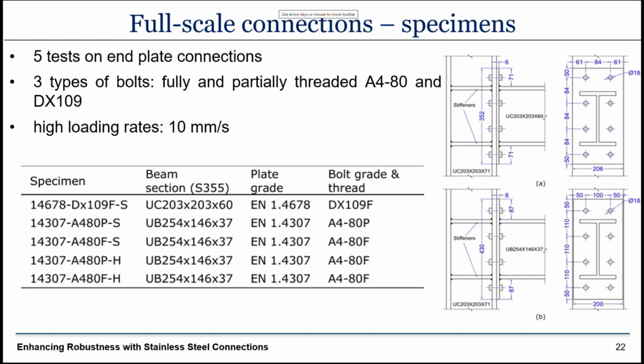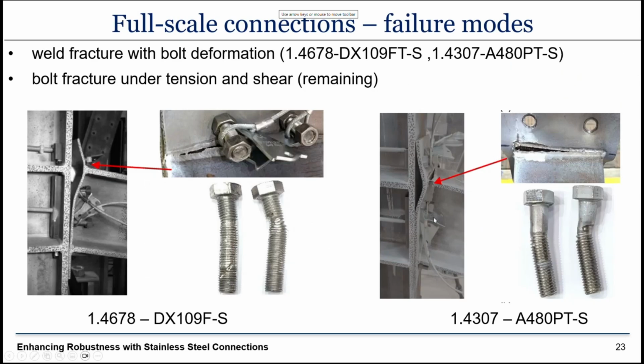So for the full-scale connection specimens, we wanted to do 6 tests. 1 specimen was destroyed by mistake, so it was tested without us wanting to test it. We got results for 5 of them, 3 under static loading conditions and 2 under high strain rate conditions. And let's move on to the failure modes, which is the more interesting part.